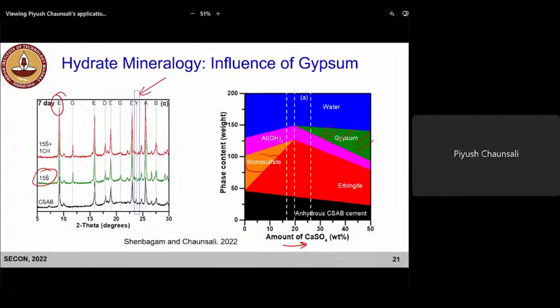So thermodynamic modeling can also predict which phases, what the stable phase assemblage will be, and that can be verified through experiments such as X-ray diffraction and TGA, because the aluminum hydroxide formed in this case is not crystalline, so X-ray diffraction cannot detect it. This can be identified using TGA.